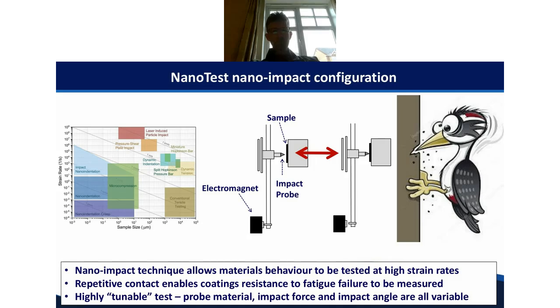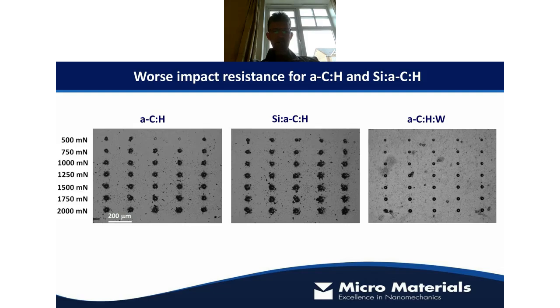So we've looked in a little bit more detail at that with our impact test capability. For those that haven't seen it before, essentially think of it a little bit like a woodpecker tapping at a material. We fire this probe in backwards and forwards, and it generates multiple high stress contacts, true impact events that allow us to fail materials at high strain rates.